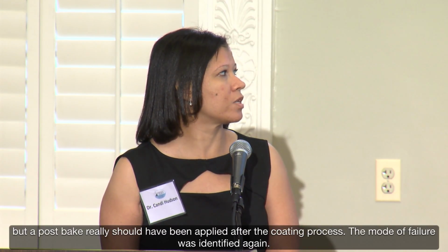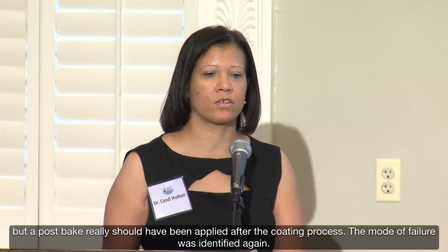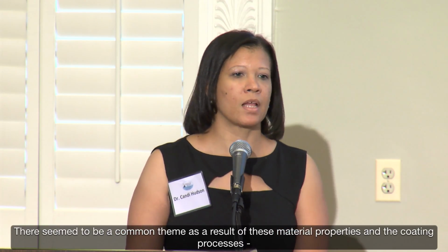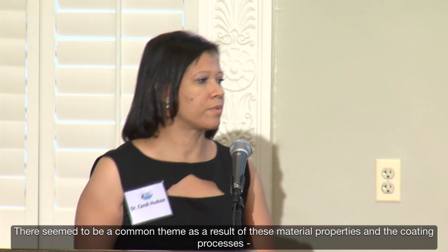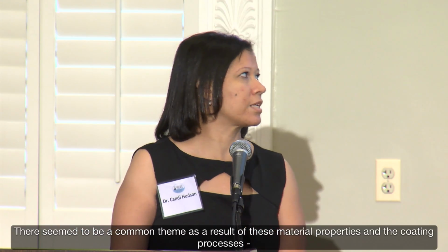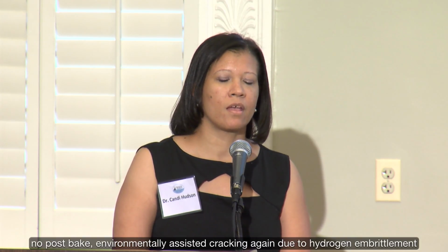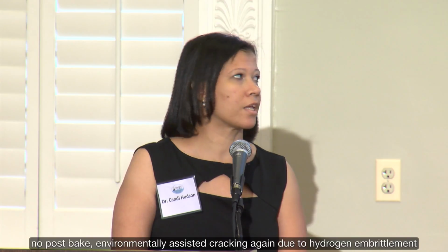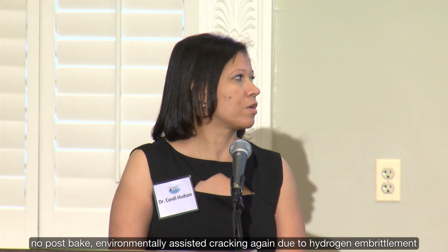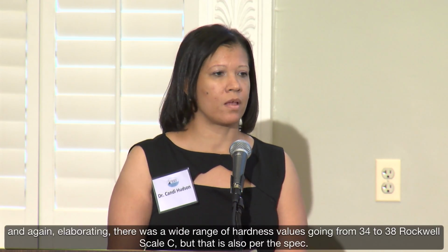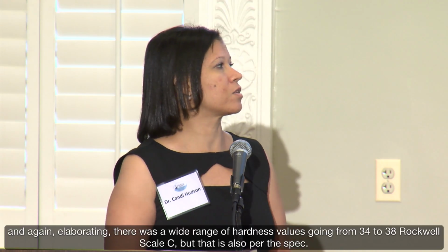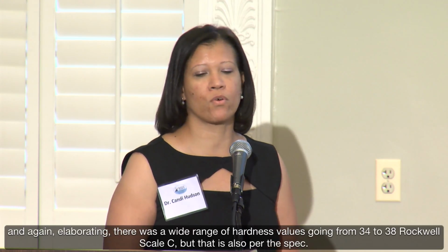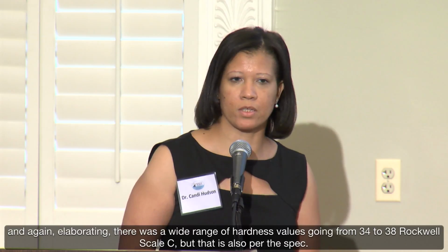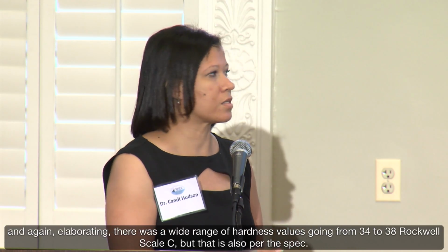The mode of failure was identified. Again, there tended to be a common theme as a result of these material properties and the coating processes, no post-bake. Environmentally assisted cracking again, and due to hydrogen embrittlement. And again, elaborating, there is a broad range of hardness values going from 34 to 38 Rockwell scale C. But that is also per the spec.